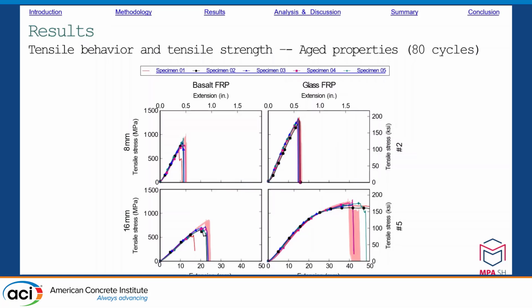The following graphs show the result of the same group after a frost load of 80 cycles. The results of the samples with 0 freeze-thaw cycles are shown in red. In the case of the basalt fiber rods, it is clear that the maximum stress values after 80 freeze-thaw cycles are lower than those that have not been subjected to freeze-thaw stress. For the glass fiber rods, almost the same stress values are achieved as for the samples with 0 freeze-thaw cycles.